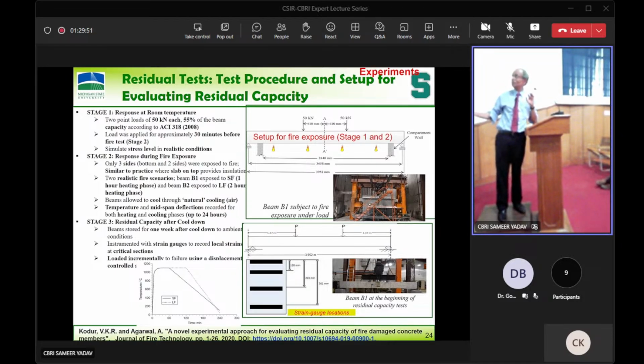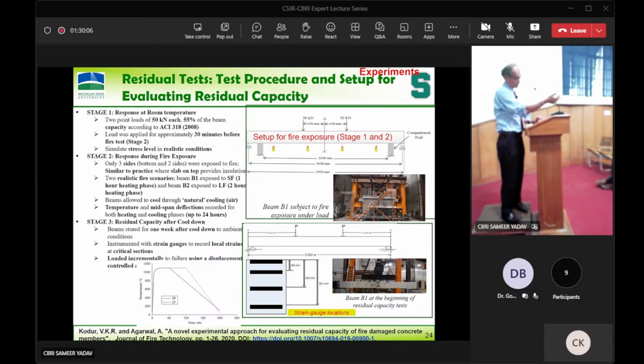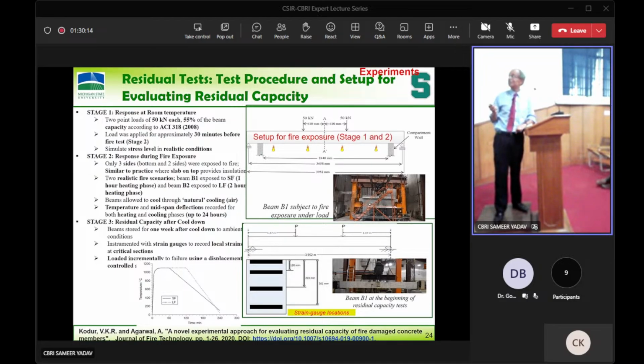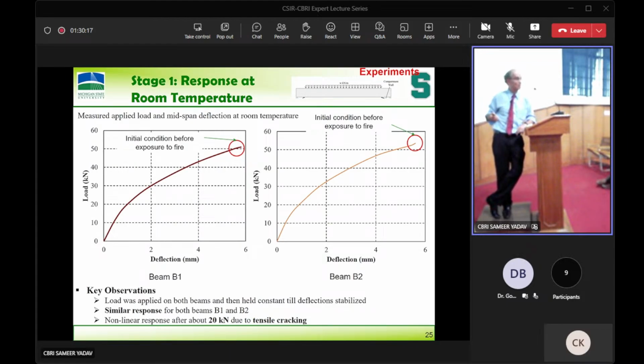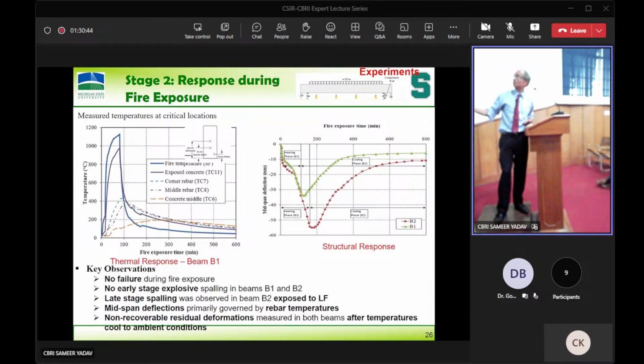Then you have to subject that beam to fire involving heating, a realistic fire, not the standard fire. Heating phase, cooling phase, whatever is present in the room. Then once you do that, after the cooling down, you subject that beam to a structural test to find out how much capacity remains. So 3 stages of analysis are required in this experimental procedure we developed in 2013 and 14. If you see here, this is the first stage. You need to apply to those beams the service loads, not the full design loads, not the ultimate capacity. You subject them to service load and find out how much deflection the beam has.